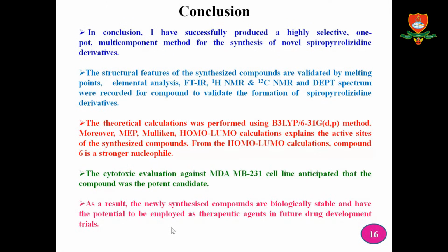Finally, I have successfully produced a highly selective one-pot multi-component method for the synthesis of novel spiropyrrolidine derivatives. The structure of the synthesized compound is confirmed by FTIR spectroscopy, NMR spectroscopy, C13 NMR, H1 NMR and DEPT spectrum. The theoretical calculation was performed using Gaussian software. The anti-cancer activity of the synthesized compound was evaluated against MDA-MB-231, a breast cancer cell line, and the compound was anticipated to be a potent candidate. As a result, the newly synthesized compounds are biologically stable and have the potential to be employed as therapeutic agents in future drug development trials.